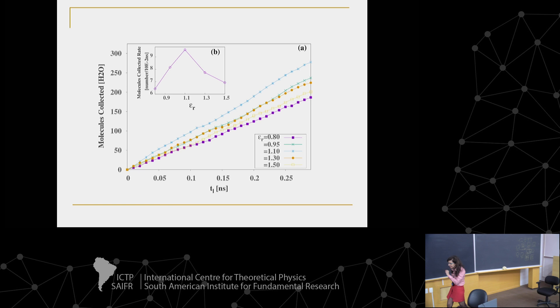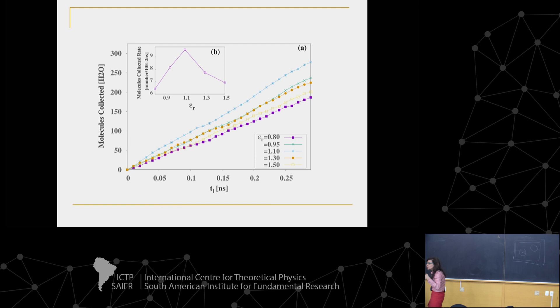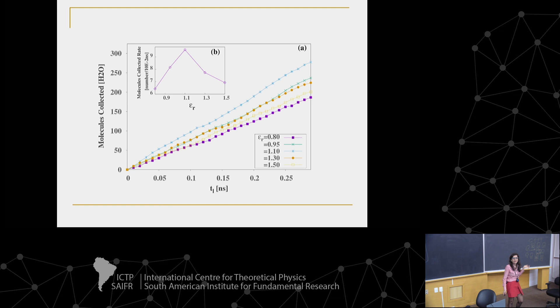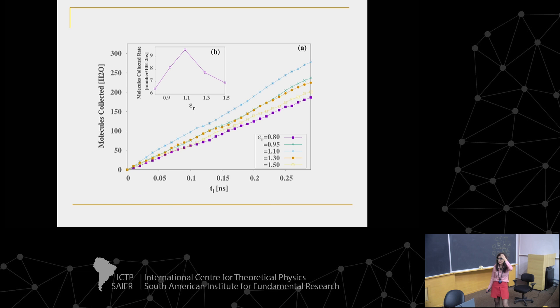There is a key trick: the hydrophilic material cannot be too strongly hydrophilic. If the material is too hydrophilic, water becomes so comfortable inside the cone that it stops moving. We tuned the interaction by hand in simulations — a benefit of theoretical work. Parts of our group are studying which real doped graphene material could serve this role in an actual cone.